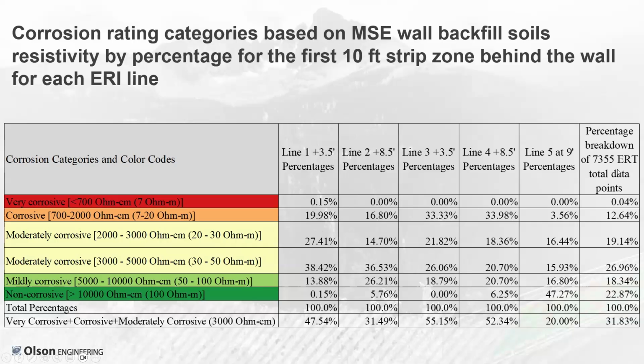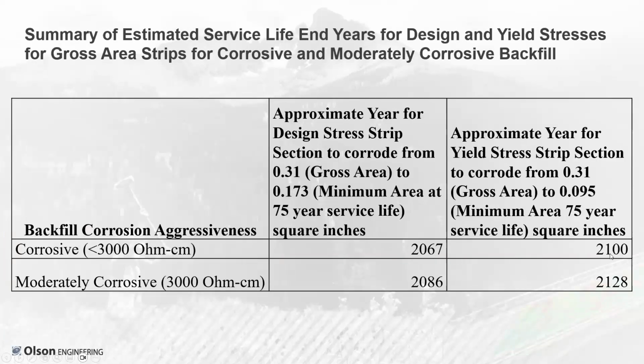So when we summed all this up of these 7,355 ERT data points, you can see the breakdown of the percentages. So in terms of very corrosive, which is the bottom line in the table, to corrosive to moderately corrosive backfill soils at this time that we measured in the field with the electrical resistivity imaging or electrical resistivity tomography results, you can see that we had about 32% that were in this category. But a lot of that, of course, was in the more moderately corrosive, with some in the corrosive range. So taking that all together, to boil it down for the project,